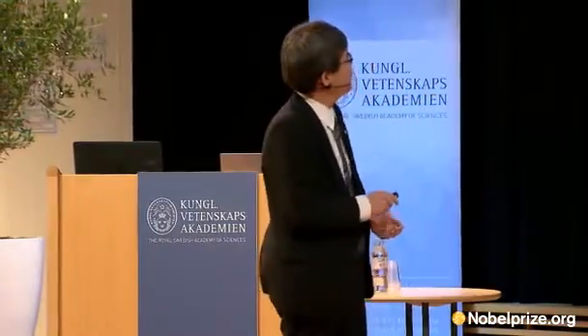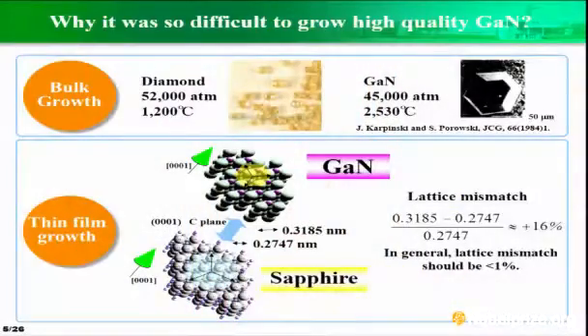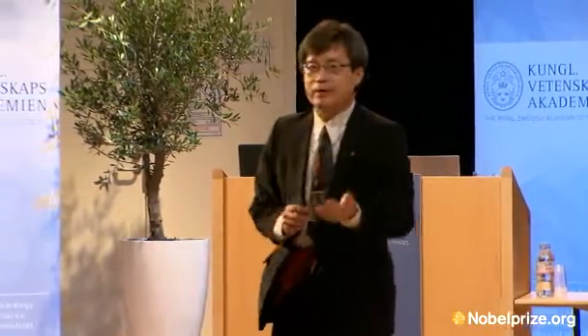I'd like to explain why it was so difficult to grow gallium nitride. If you want to grow large size bulk gallium nitride, you need high pressure and high temperature, which is similar to the synthesis of diamond, or even higher. So you need to use chemical reaction to reduce the pressure and the temperature. In addition, you need a foreign substrate for the epitaxial growth of gallium nitride.